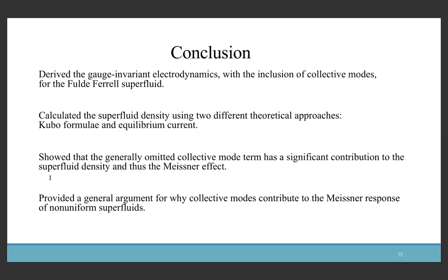Well, I know in 2001, they were looking at these Josephson junctions with ferromagnetic interlayers, and they measured these 0-pi oscillations. So for about 10 years, all over the literature, we still don't know if this is the Fulde-Ferrell-Larkin-Ovchinnikov effect. And then when long-range effects came out that same year, that was even more like, oh, we don't know, we have no idea. It could be, could not be. So I've heard this in various things. Yeah, there are a lot of other effects in that field that aren't perfectly well characterized.